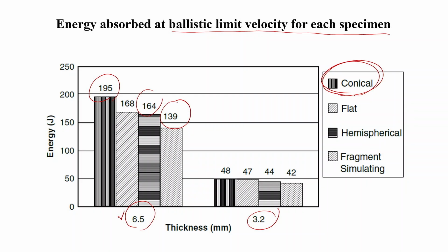Fragmented absorbs the least energy. A similar trend is also observed for 3.2 millimeter thickness. So, for the fragmented projectile, the energy absorption will be least.